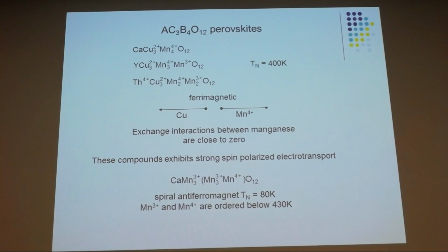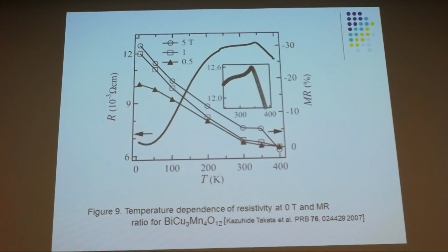The optimally doped compound, calcium manganese, is a spiral antiferromagnet. This transition, and this compound, was first synthesized by our group. This is resistance and magnetic resistance in the bismuth copper manganese 3,4,12 compound. This compound also was first synthesized in our group. It exhibits transitions at the Curie point and at the Néel point, and similar magnetic resistance to standard manganites. Ferromagnetism, but the overall picture is similar.